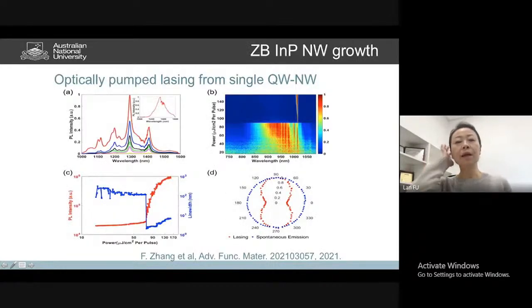Nice image. So with these beautiful radial quantum wells and also uniform quantum wells grown, if we pump them hard enough, we actually can achieve room temperature lasing from the quantum wells. So you can see this 1.3 micron emission lasing from our quantum well, showing the good material quality.